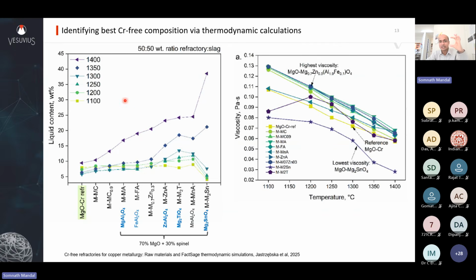So from that liquid you get the liquid phase percentage. This is this plot, and it also gives you viscosity values, and from there you plot the viscosities, and then you can compare one refractory versus the other. So this is the theoretical simulation or prediction of viscosity. This is not real viscosity.